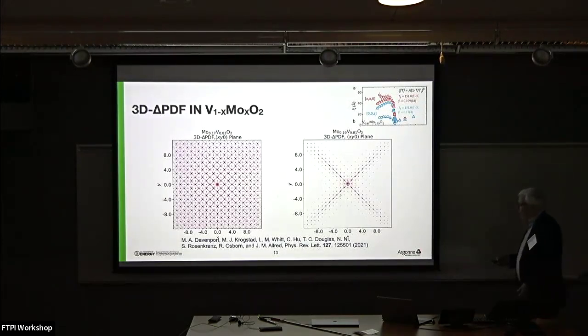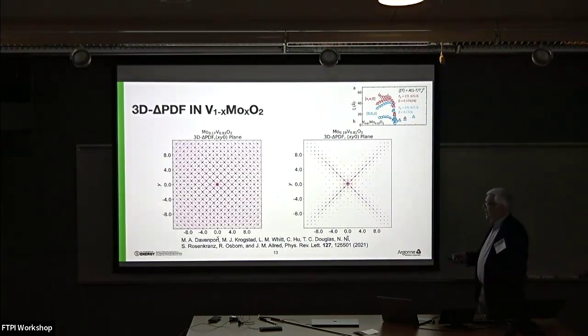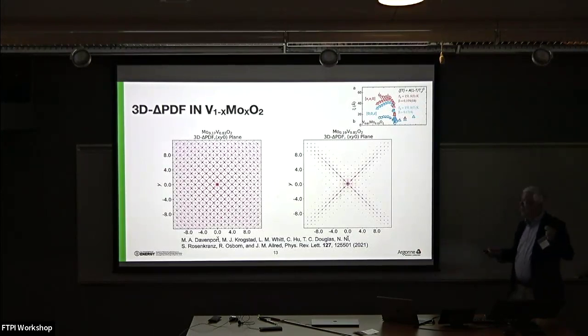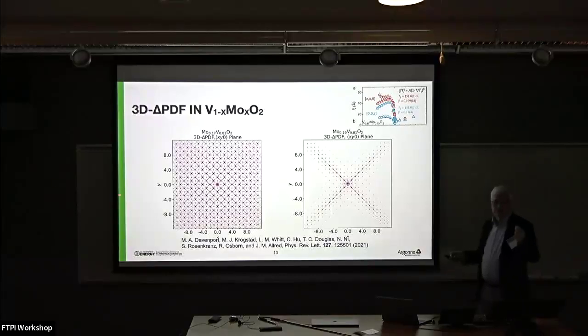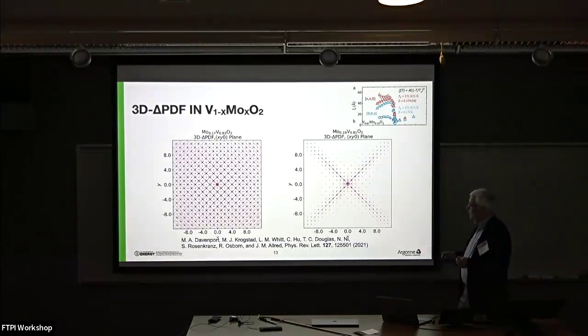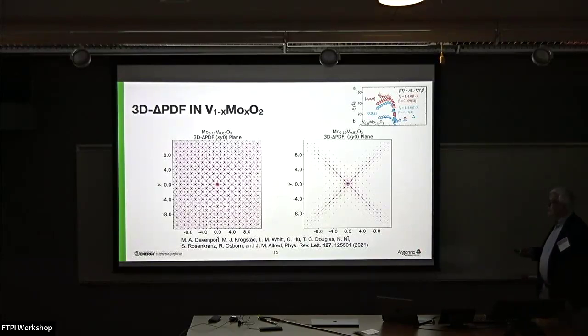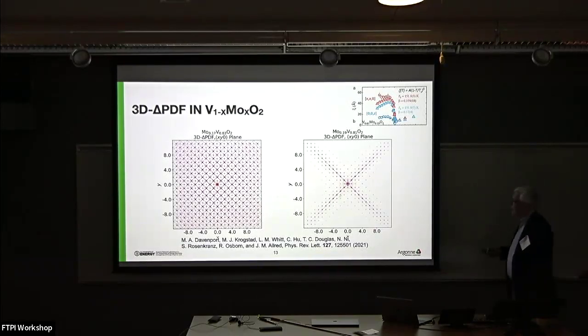If you look at the M1 phase, you have essentially long range order. You see, we haven't punched out the M1 peaks here. We haven't punched out the superlattice peaks, so we can see long range order. These are all peaks that arise from distortions from the rutile structure in the M1 phase, and they persist over very long distances. In the 19%, we now only see these correlations in two-dimensional planes, and in fact we only have a finite correlation length along the 1-10 directions of around 50 angstroms, which is determined by how the peak intensity exponentially decays, and it's only about 10 angstroms transverse.